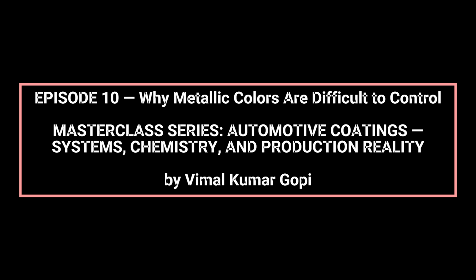Pigment-binder interactions also play a critical role. Inadequate wetting or poor dispersion efficiency increases flake interaction, promoting agglomeration and local orientation differences. These effects often manifest as patchiness or sparkle non-uniformity across large panels.